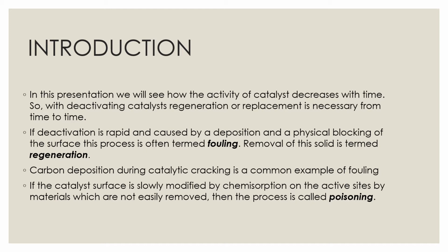If deactivation is rapid and caused by a deposition and a physical blocking of the surface, this process is often termed fouling. Removal of this solid is termed regeneration. This is how we get rid of the deactivation in the catalyst. The carbon deposition during catalytic cracking is a common example of fouling, which deactivates the catalyst and affects the yield of the product in a reaction.